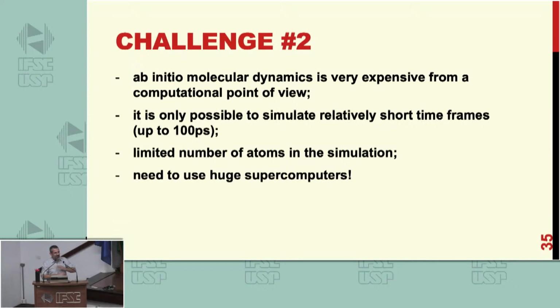So we can only run very small time frames, of the order of 100 picoseconds, in this kind of simulations. We can run a few hundred atoms, 300, 400, 500 atoms, using the largest supercomputers we have available. So we use this Santos Dumont supercomputer in Petropolis. We usually use hundreds of CPUs for weeks to run this kind of calculations. So they are very, very expensive, okay? And this limits the applications that we have, okay?